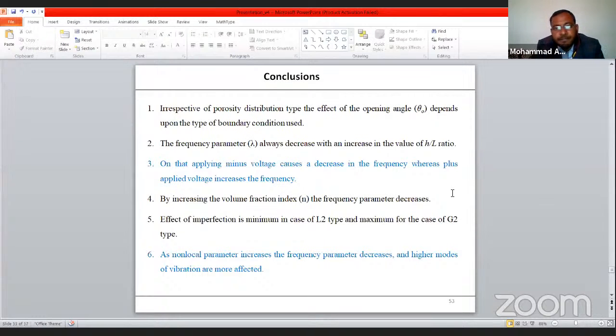Now moving to the conclusions. Irrespective of the porosity distribution types, the effect of opening angle depends upon the type of the boundary condition used. The frequency parameter always decreases with the increase in the value of H by L ratio. From this particular statement, we can also further conclude that thin structures have higher frequency parameter than a thick structure. On applying the minus voltage, it causes decrease in the frequency parameter, whereas on applying the plus voltage, the frequency parameter will increase.